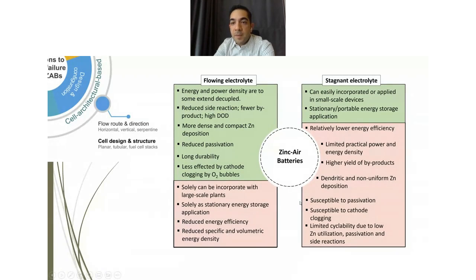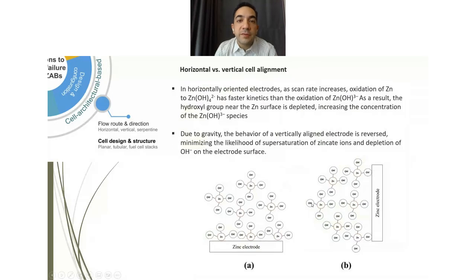And okay, so jumping into different cell orientations, like horizontal or vertical, the main thing to highlight here is the effect of drag force and gravity. So when the electrode is oriented vertically, the heavier precipitates can fall down and be removed from the electrode surface, while in the planar horizontal type, they will accumulate on the surface of the electrode. So a different product of zinc will result when using horizontal or vertical cell electrodes.